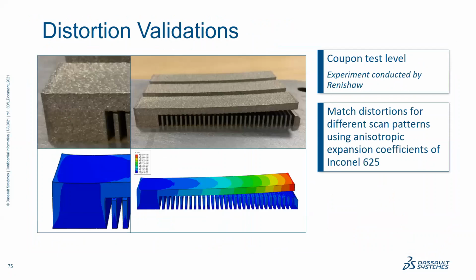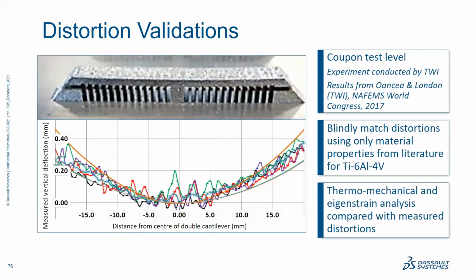So just to show in more fine detail, you can see here the part which was printed, the distortions or the distortion profile matches to a reasonable level, taking into account the anisotropic expansion coefficients for the Inconel 625. So this double bridge cantilever, you can see there were some blind match distortions which were done. That is, the simulation did not have the experimental data, so a blind simulation was done, and then the result matched very well with the test data. So there was no way by which the model could be tweaked. So the model that was incorporated and used upfront was able to capture the test data to a very good accuracy. And so the thermomechanical eigenstrain analyses were compared with the measured distortions in both the cases to validate it.